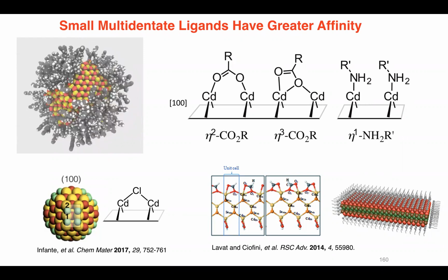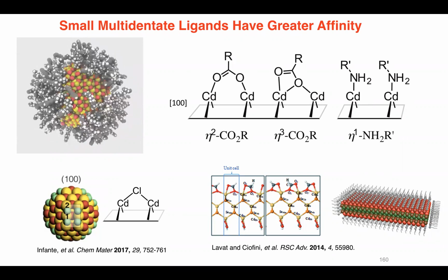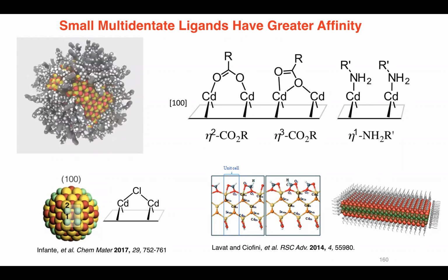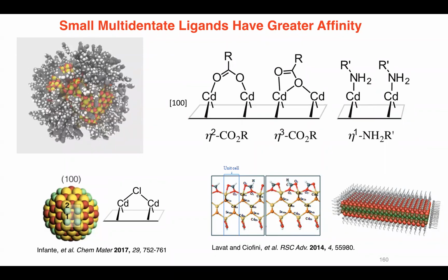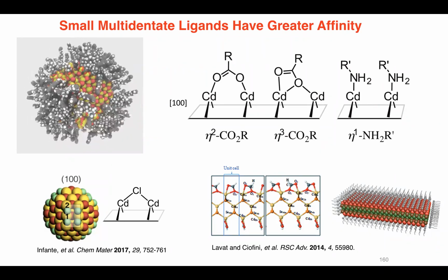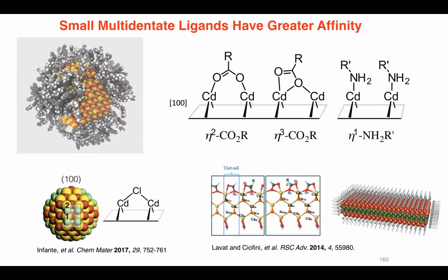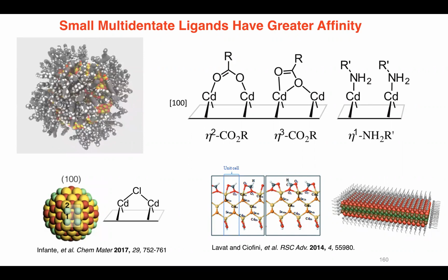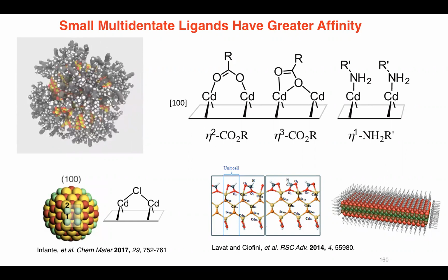Chemistry happens when, like in catalysis science, if you're doing palladium cross-coupling, palladium becomes reactive when it becomes low coordinate. Okay, these are very energetic kinds of arrangements. This is a very unnatural position for cadmium to be found in, and that helps explain why a carboxylate anion would outcompete a primary amine for binding the nanoparticle. There are binding sites that do not match that simple monodentate thing, and where a bidentate thing is much more effective.